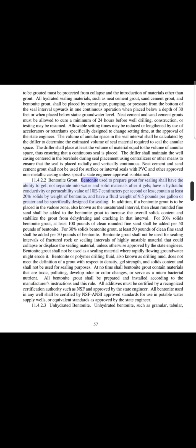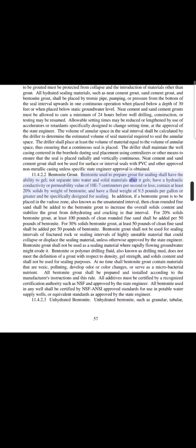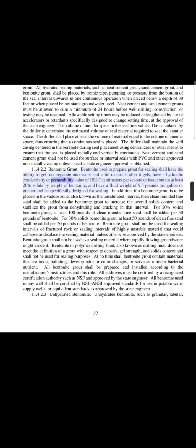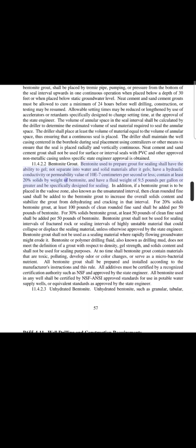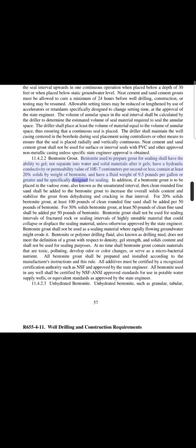11.4.2.2 Bentonite grout. Bentonite used to prepare grout for sealing shall have the ability to gel, not separate into water and solid materials after it gels, have a hydraulic conductivity or permeability value of 10 to the minus 7 centimeters per second or less, contain at least 20% solids by weight of bentonite, and have a fluid weight of 9.5 pounds per gallon or greater, and be specifically designed for sealing.